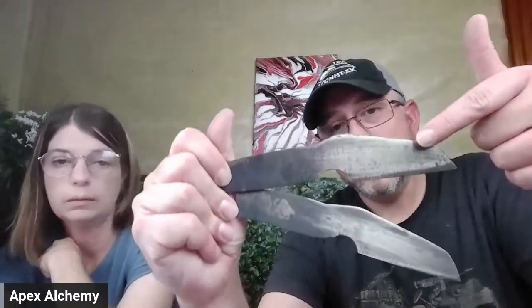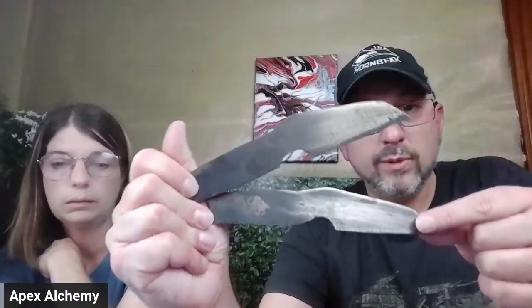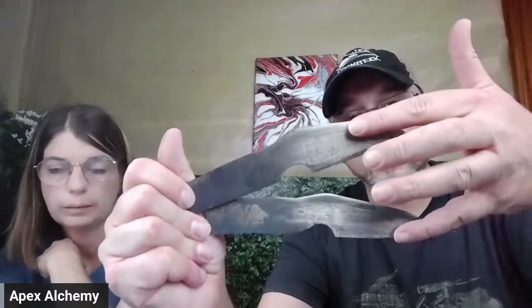So I knew it needed to be tempered. I threw them both in the oven at 325 degrees for one cycle. I get them out, and they are 59 and 62. But both of them were 65 post quench. So what do you think about that? I'm not a heat treat expert. I'm just learning. Both of them were warped too, but it doesn't matter.